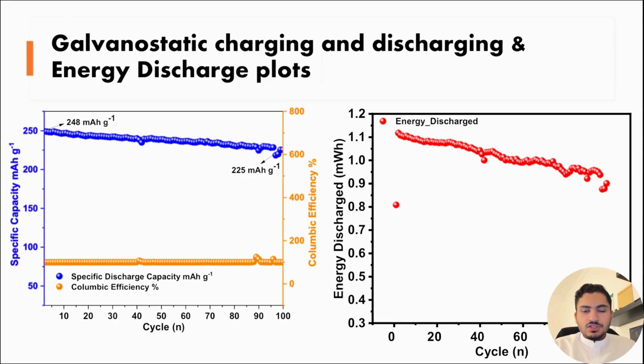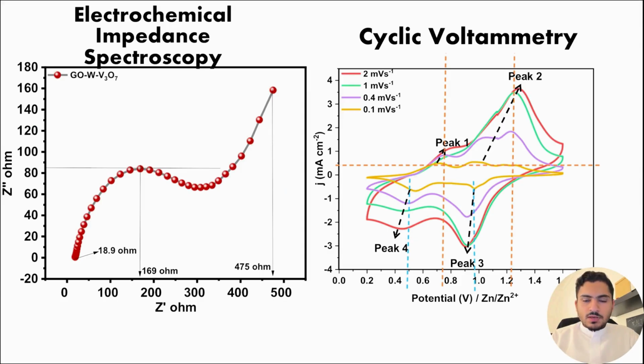Next is the galvanostatic charging and discharging and energy discharge plots. On the left, we have the GCD, where we activated the battery for about 2 cycles. Then we measured the specific capacity, which returned about 248 mAh per gram. After 100 cycles, it dropped to 225 mAh per gram, and the testing is still going, as you will see soon in the video. Throughout the entire process, we maintained an efficiency of about 100%. On the right, we have the energy discharge plot, where we started with about 1.15, and after 100 cycles, it dropped to 0.85.